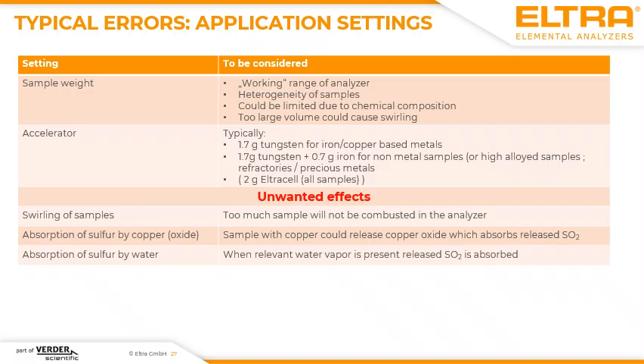When you now would like to start with carbon sulfur analysis of your powdered sample, you have to ask yourself different questions. What is the working range of my analyzer? Because when, for example, you have a carbon-rich sample, you have to consider the approximate carbon concentration, and then you have to adjust the sample weight. You also have to think about the heterogeneity of the sample, because when you have a very homogeneous sample, it's maybe allowed to apply very low sample weights between 50 or 100 milligram. When it's a little bit more heterogeneous, then maybe it's suitable to increase the sample weight up to 100, 250 milligrams. More is maybe not allowed, because otherwise you will have a swirling of the sample.